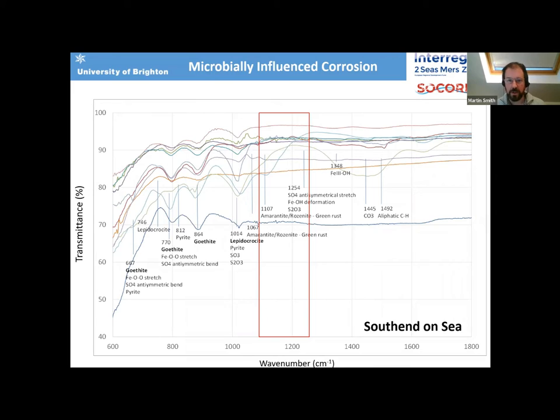So when we get into tidal corrosion without, we suspect, strong bacterial influence, we're not seeing the sulfur species absorption in infrared spectra. So we have a fairly rapid route for assessing the mineralogy to check for sulfur species. And this is something we want to develop further into a rapid assessment technique for risk assessment, for feeding the risk algorithms. This is great, but it has been on bulk samples or purely directly onto the surface of corrosion. What we want to do is understand the structure of those blisters and tackle the actual mechanisms of what is causing this accelerated corrosion process.